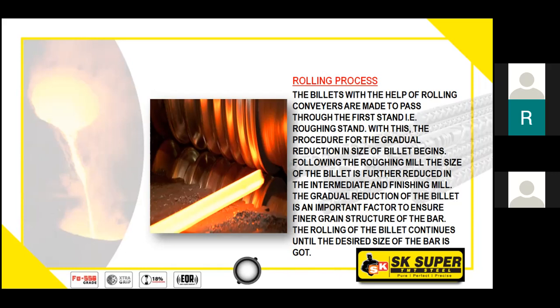Now, up till here, the temperature of the bar from 1150 degrees in the billet process comes down to a temperature of 900 to 950 degrees centigrade. This all practically happens within a minute. This, right from the billet when it comes out from the billet plant till the finishing stand, the time taken is not more than 1 to 2 minutes.